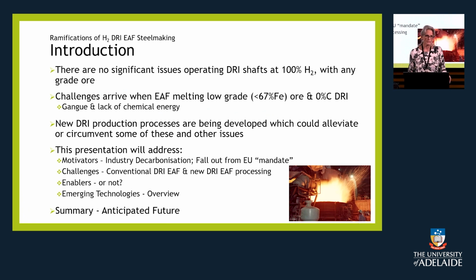There's no real significant issues operating DRI shafts at 100% hydrogen. The problem becomes when we try and process the DRI through the electric arc furnace, especially if we're going to 100%. The challenges are potentially the gangue and the lack of chemical energy in the DRI. Now, new production processes are coming to the fore, which hopefully will alleviate or postpone or circumvent some of the issues that we have, but we will see.